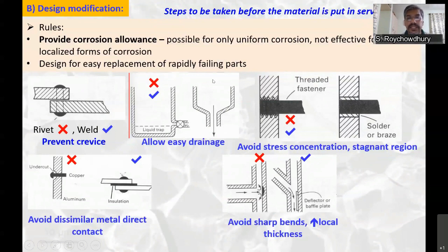Allow for easy drainage, like this is a tank. I'm sorry, this stick should have been here. So this is a better design. When the design is such that it will empty completely, there will be no stagnant pockets. Whereas in this design, this is not good. Even though you try to drain, it will not drain out completely and there are liquid traps. If you have a threaded design, they act as locations of stress concentration, which is not good. Also, it provides a stagnant region. So instead, avoid threaded joints, rather solder, braze, or weld wherever possible.